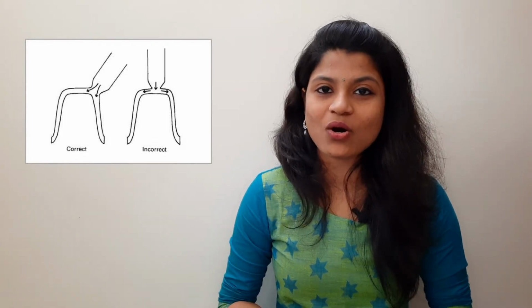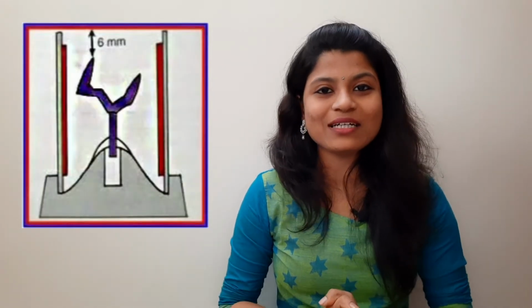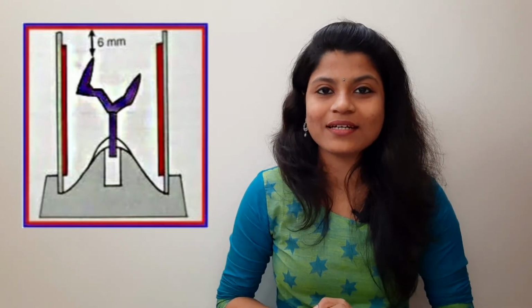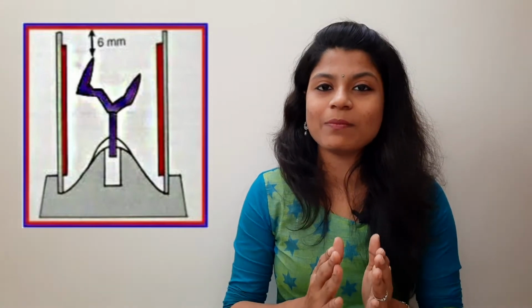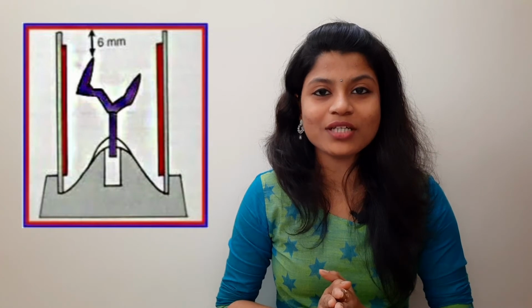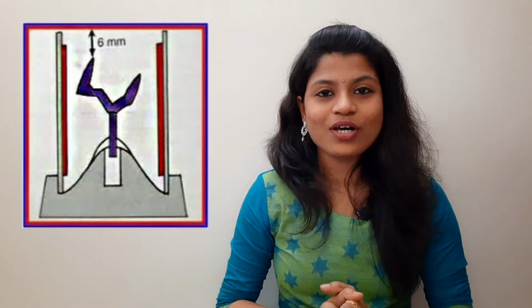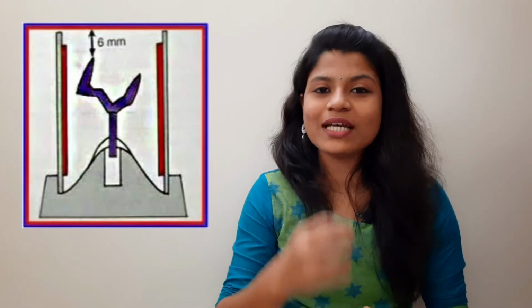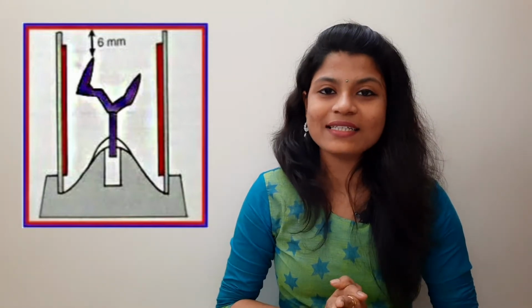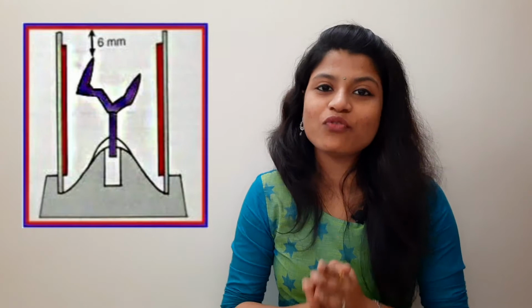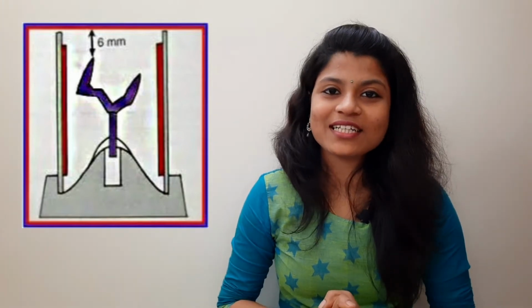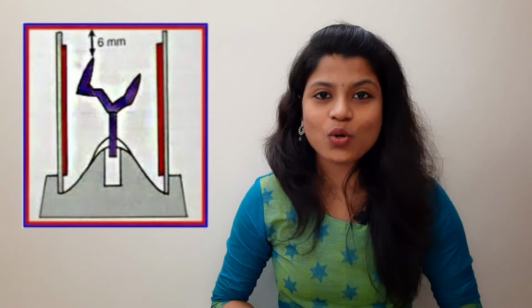The length and diameter of the sprue depend on the type and size of the pattern, the type of casting machine to be used, and the diameter of the casting ring to be used. The diameter of the sprue should be equal to the thickest portion of the wax pattern, and it should be attached to the bulkiest part of the wax pattern but not near the margins and occlusal contacts. The larger the diameter of the sprue, the better the flow of the molten metal into the mold, and with a smaller diameter, it solidifies before even casting and results in porosity, and this porosity is known as suck back porosity.